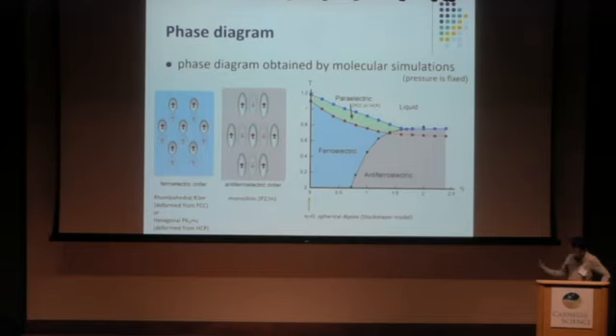In the paraelectric phase, the particles form a crystal, but the orientation is disordered. Sorry, I forgot to explain, but the orientation of the dipole moment is parallel to the long axis of the molecule. And in the paraelectric state, the particle orientation is completely random in FCC or HCP configuration. So in this model, in the paraelectric phase, FCC and HCP have almost the same probability. And for small anisotropy, decreasing temperature, orientational ordering occurs at a certain temperature to form the ferroelectric phase in the left one.